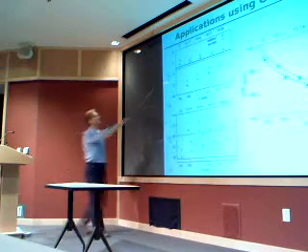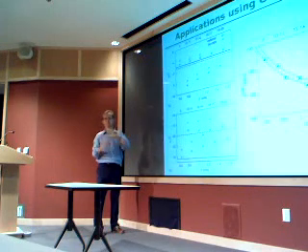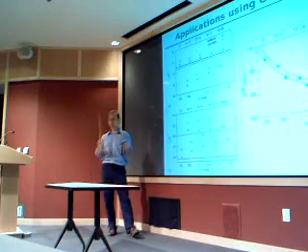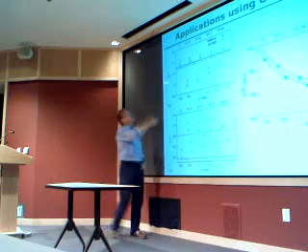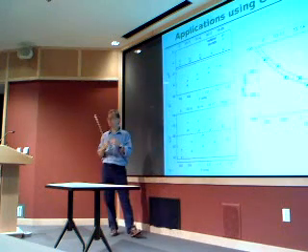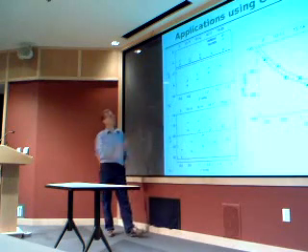Another application is carbon nanotubes. They first calculate the magnetic susceptibility, along and perpendicular to the tube. If you know carbon nanotubes, they're these one-dimensional objects kind of wrapped from graphene. And this is as a function of the diameter of the nanotube. The bigger the nanotube, you start to converge towards some value. These two are how close the nanotubes are to each other. You know, it's very difficult to isolate a nanotube. So what they calculated was both isolated and then bundled and then interacting. Qualitatively they have the same values.